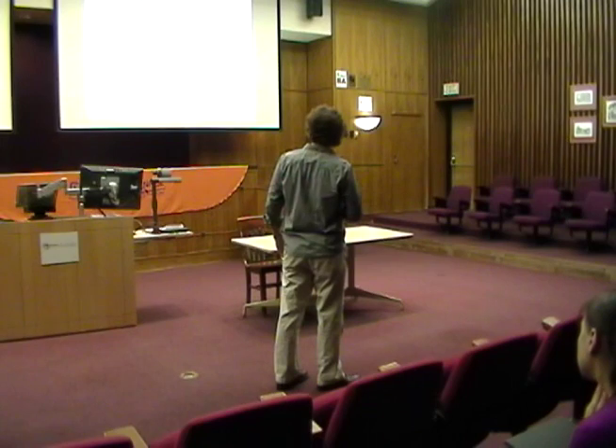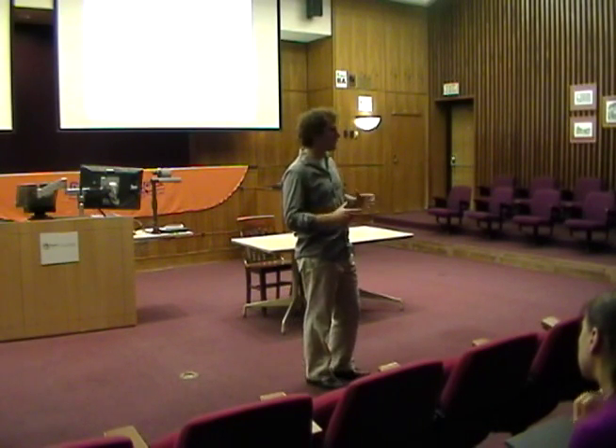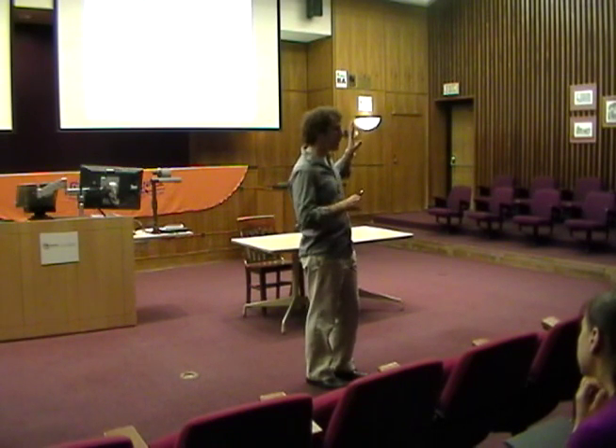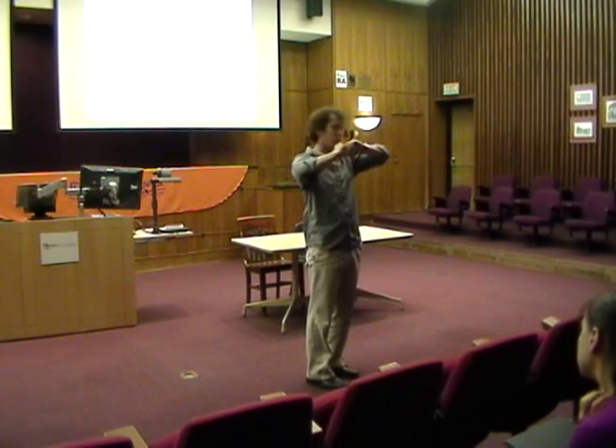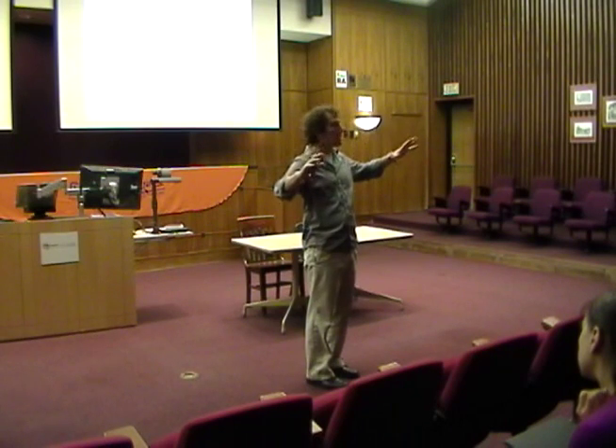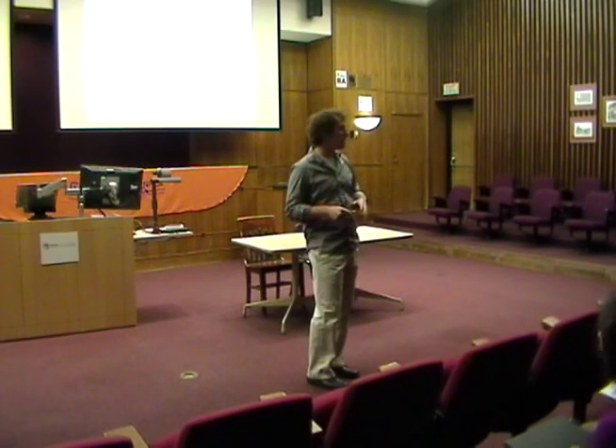So this depends on the cooling system, whether you use an active cooling system or a passive cooling system. This is a laboratory measurement, so it's sitting on a thermoelectric stage that's trying to cool it to 25 degrees. This is an indoor measurement under what's called a flash simulator. You generate this kind of high intensity by taking a discharge lamp and flashing it, collecting all the light onto the cell and measuring your IV curve in 3 milliseconds. So it's not quite the same as outside. Outside you have other problems with the spectrum and with cooling.